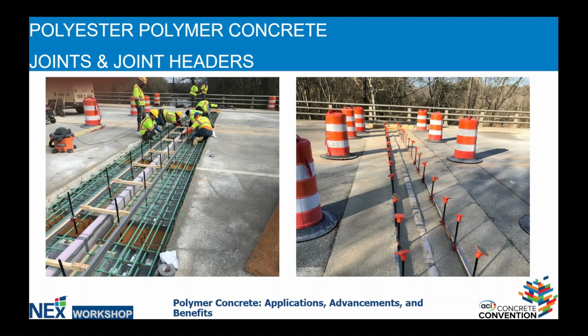Here's an example of some joint headers that are being filled with the PPC. In the case on the left, you've got a highly reinforced joint header system, and of course the joints are where the punishment occurs. As the traffic is moving across those joints and hits whatever the expansion mechanism is that allows for the movement, it's the joint headers that tend to be the weak spot due to the impact of 55, 65, 75 mile an hour traffic. There's always a movement capability built into those joints, of course, for expansion and contraction purposes, typically a foam type of expansion joint.